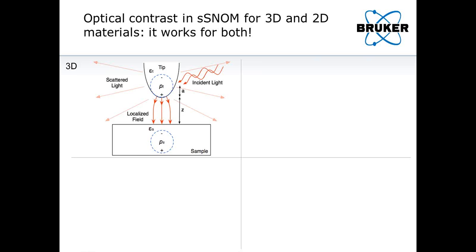The effect of the sample on the evanescent waves produced by the tip is that the sample surface will reflect these waves, and these waves will then drive more charges to the tip, or they may destructively interfere and actually cause the tip to have a smaller polarization.